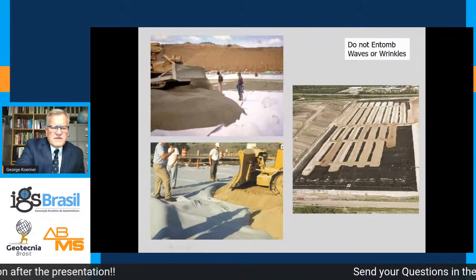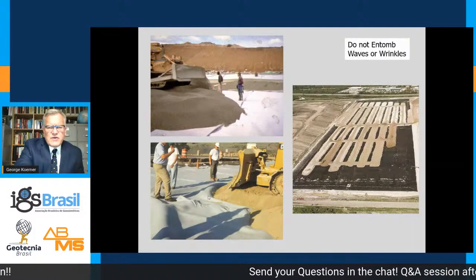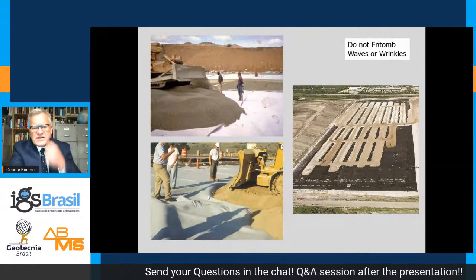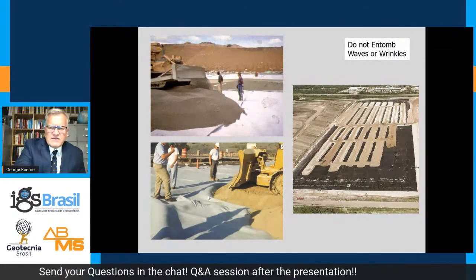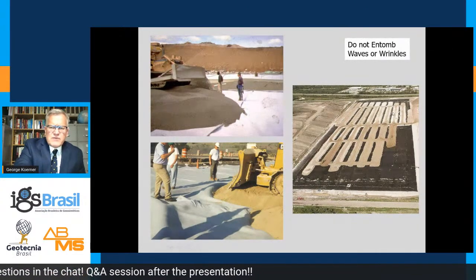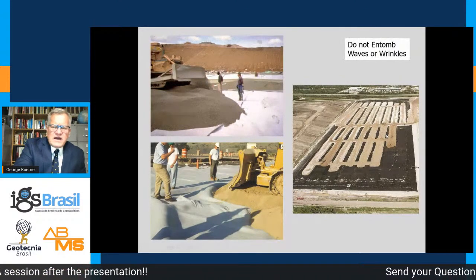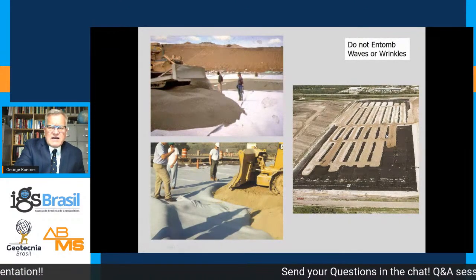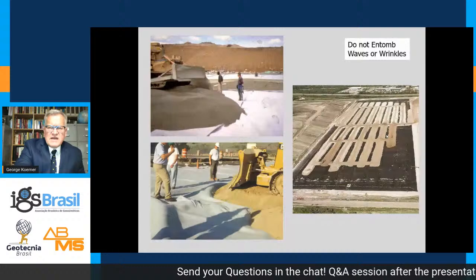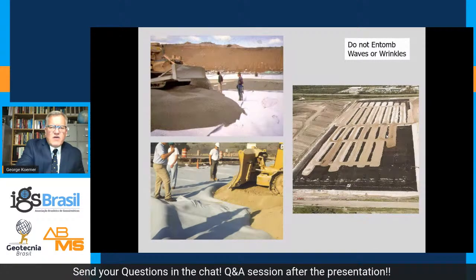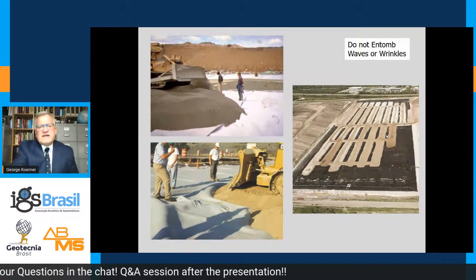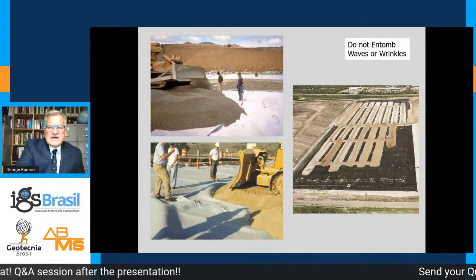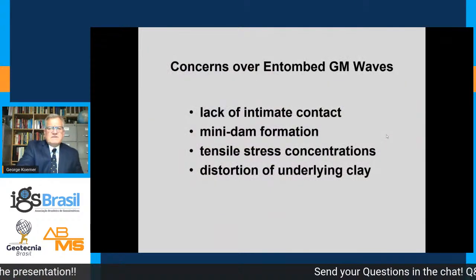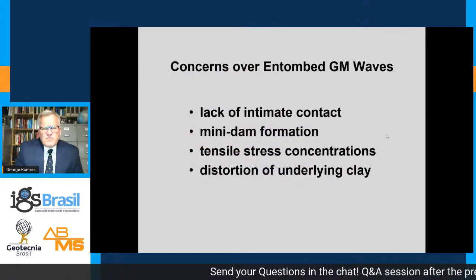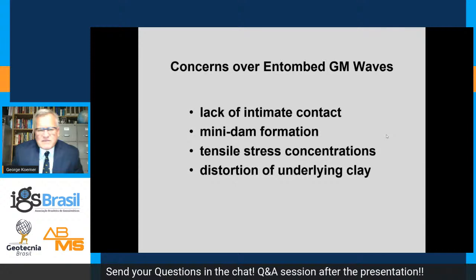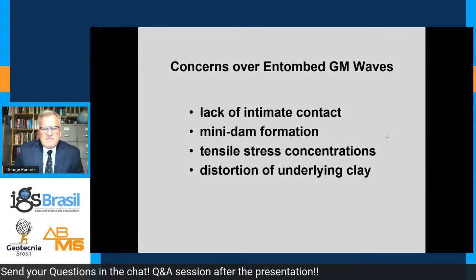It needs to be cut out and flattened, or you have to wait until a cooler period of the day until you continue this covering. You might want to stage this work incrementally so you get distributions of the wave. There's a right way to do this and a wrong way, and certainly you need a press fit of the geomembrane against the underlying material. Concern over entombed waves is certainly lack of intimate contact, which we described the theory.